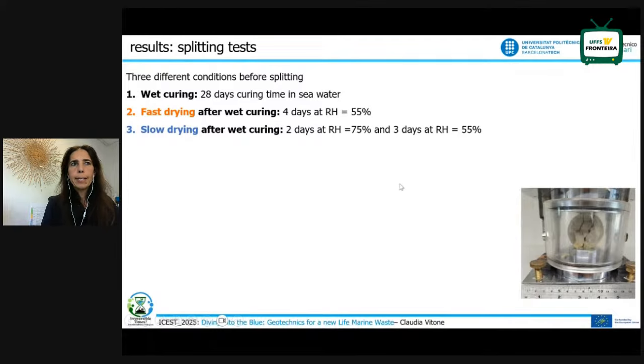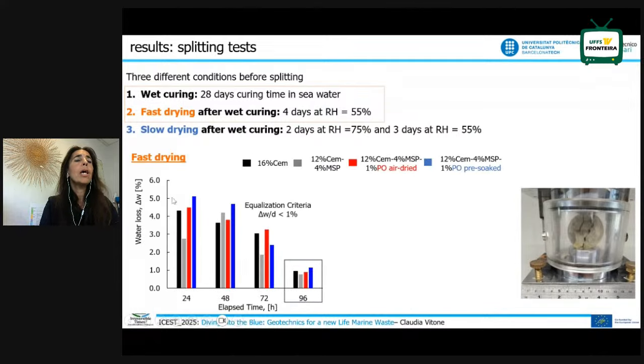Now some splitting tests, to see if these fibers are also working and improving the mixtures during splitting tests. We have tested 3 different conditions, but we will focus on just wet curing and fast drying. In particular, fast drying was carried out leaving the mixtures for 4 days at relative humidity 55%. This is the water loss plotted against the elapsed time. The equalization criterion was that the water loss has to become lower than 1%, so we could wait 4 days.